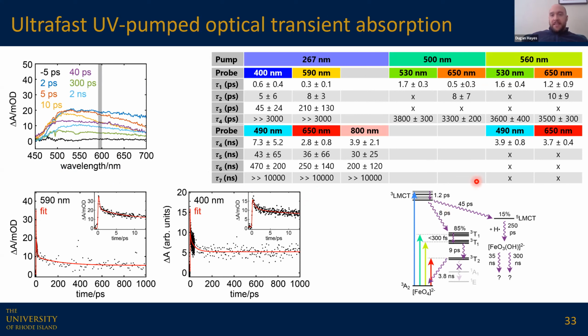But basically what we see is 8 picoseconds for internal conversion to these triplet T1 metal-centered states versus 45 picoseconds for intersystem crossing to this quintet LMCT state, which gives us a branching ratio of about 85% into the metal-centered state and 15% into the quintet.